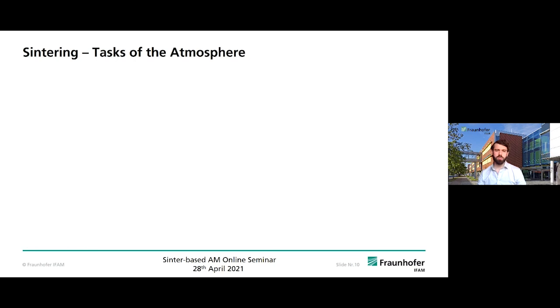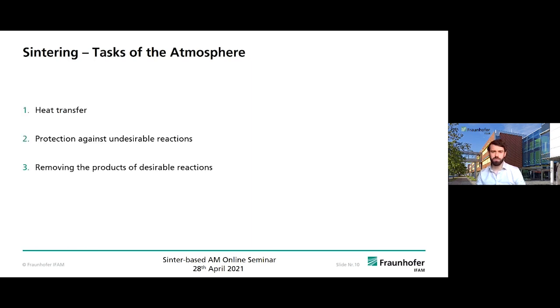And then there's the atmosphere. And I would say this might even be the more important point compared to the temperature. The atmosphere has some tasks. First of all, it's heat transfer. You have to get the heat from the heating elements to the parts. Then it also should protect the green parts against undesirable reactions like oxidization, decarburization, or carburization. And the third part is removing products of desirable reactions, like debinding, for example.